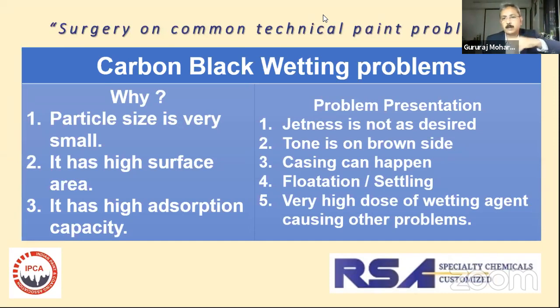How does it present? What are the effects if the carbon black is not wetted well? It presents as the jetness, the blackness that is desired, is not achieved. The tone doesn't become clean; it becomes dirty. It goes on the browner side and not the bluer side. Sometimes problems like casing can happen, especially if you have an injection molding or injecting system of application. You can see problems like flotation or settling also.